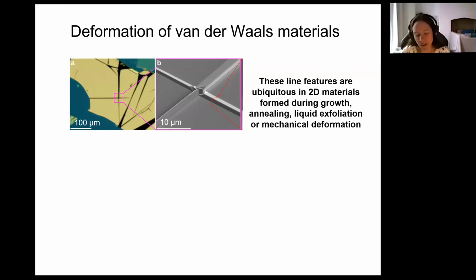We've experimented with helium, argon, krypton and xenon, and we see the same structural changes. So it really is down to the mechanical changes in the specimen and not to a chemical interaction with the implantation material. Okay, so now I wanted to go back to having a more detailed, atomic resolution look at what's going on in these kink bands.